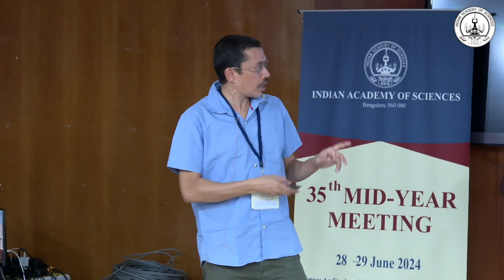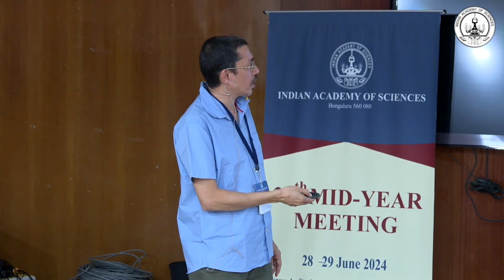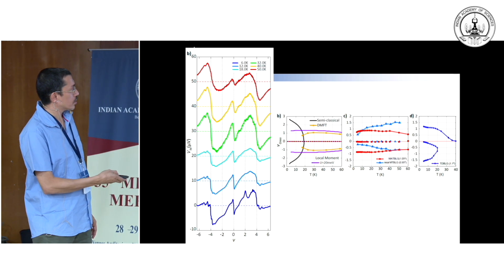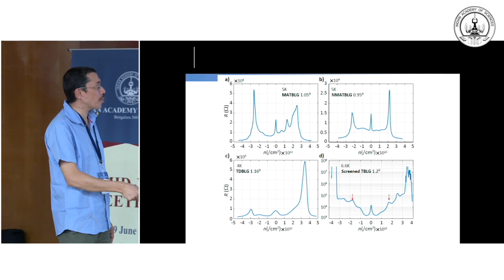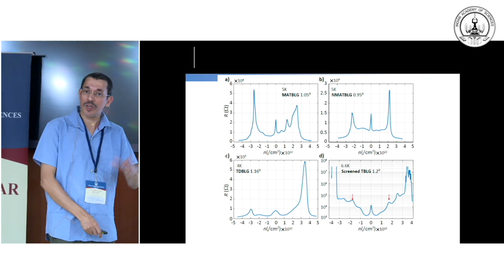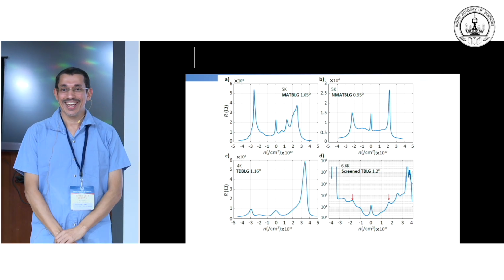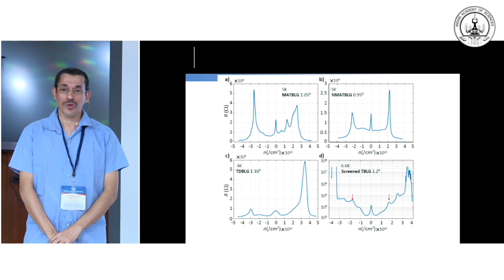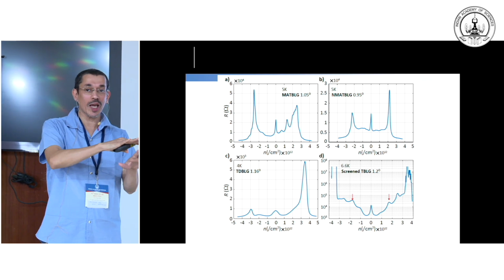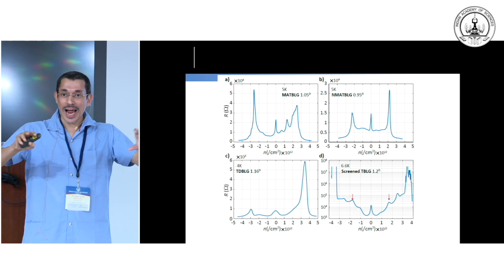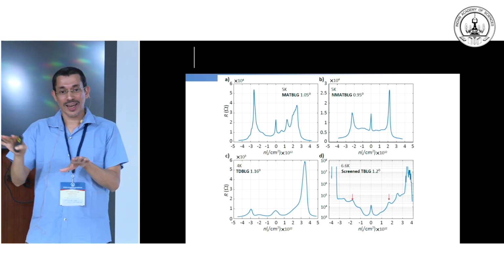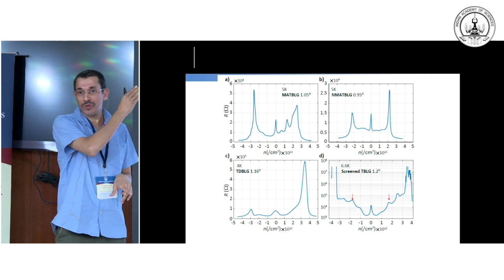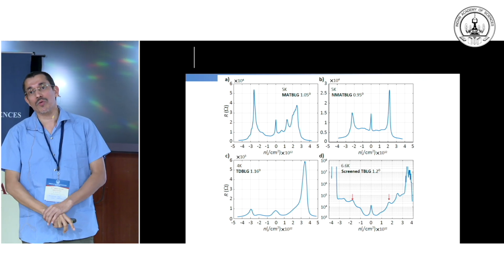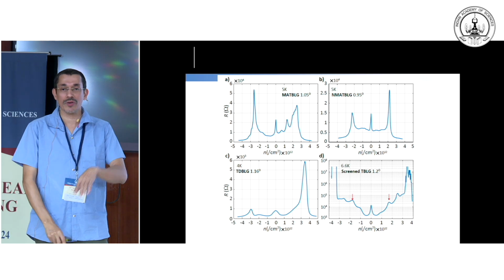So in our laboratory, so far we have hit more than 4 devices. These are the 4 near magic angle devices we have hit, but after making maybe 20 devices. So experimentally it's really challenging to hit. That is not the case with twisted TMDs. In TMDs, even at 2 degrees or 3 degrees, the flat bandwidth doesn't change much, and there is still interesting physics. But in graphene, if you want to see the magic angle physics, you have to be close to around 1.1 degrees, which is very hard compared to TMDs.